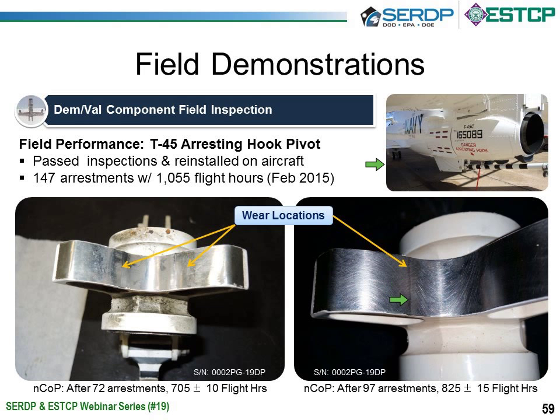With the existing pivot assemblies in chrome plating, this wear area goes to base metal. And once it reaches base metal, that item is rejected and sent back to depot for overhaul. So we're tracking this to determine how long this particular technology will improve performance in the field as compared to chrome plating. At the moment, we're getting excellent results. These are more like burnished areas. They look like wear, but they're very thin. From our last update, and we have another one due since it's the end of the FY, we've had over 147 arrestments and 1,000 flight hours. We expect that number to be a little bit higher now that some more time has gone by.